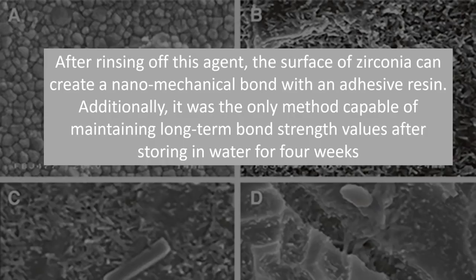After rinsing off this agent, the study said the surface of zirconia can then create a nanomechanical bond with an adhesive resin. So understand this. The studies went back and compared IvoClean to water, alcohol, and phosphoric acid, and it totally shined.